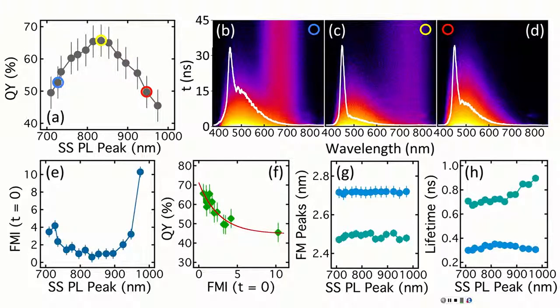When you say it's a band structure, it looks like the size of the quantum dot is at least one order of magnitude larger than the primitive unit cell. So the bulk picture probably is valid, at least for 4 nanometers. If you go to 1 nanometer, it's becoming pretty much... No, because if you go to a smaller size, you wouldn't see any PL if this was bulk, right?